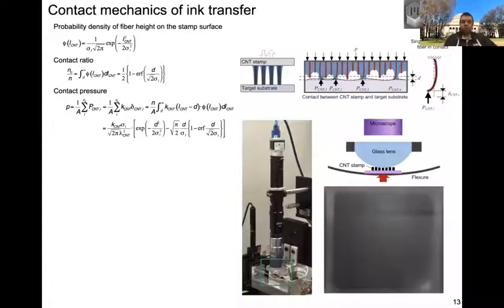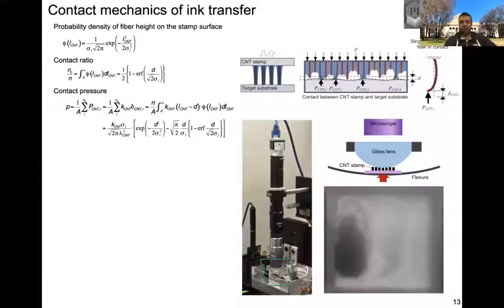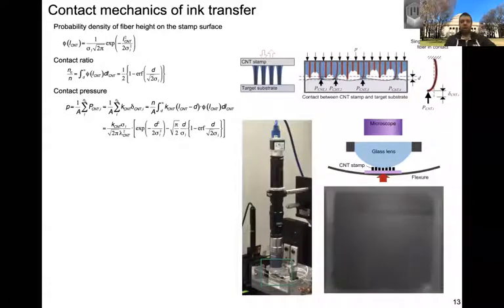And we spent quite some time studying the contact mechanics of the process. It's one thing to make the process work, another thing to understand how it works. And the best approximation is imagine the top surface of this wet CNT forest holding liquid. Like imagine a mountain range that was filled with liquid, but the liquid is sort of conforming to the surface of the mountaintops. Here the mountaintops are the CNTs, and here's a video through a microscope setup we built that's showing the contact of the wet CNT stamp with the substrate, and basically proves that as the contact evolves, all the CNTs contact the substrate you're printing on, you get a wet interface, and then you withdraw it and you get printing.